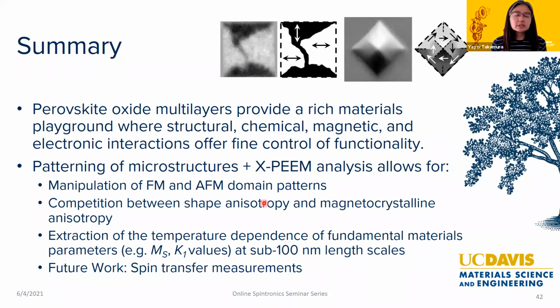PEEM is a really strong technique where we can locally extract magnetic parameters of materials, nanostructures and microstructures, with sub-micron, 100 nanometer length scales, and do things as a function of temperature. You can also apply voltages and magnetic field pulses, so you get a rich host of information, not just pretty pictures.